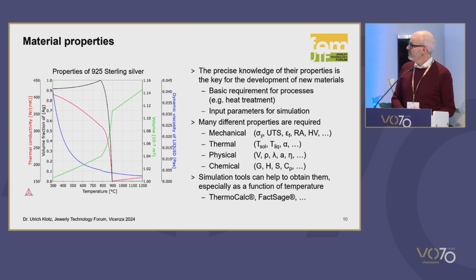And what parameters are around? We all know the mechanical parameters. They are quite easy to determine: tensile stress, elongation, hardness, reduction of area, and so on. Thermal properties we are also aware of: solidus, liquidus temperature, thermal expansion coefficient, and those properties are also not so complex to determine. But for the simulation tools, we need properties we are maybe not aware of, physical properties: the volume as a function of temperature in the solid and the liquid state, the density, the thermal conductivity, the thermal diffusivity, the viscosity, and also some chemical properties like Gibbs free energies, enthalpy, heat capacity. These properties are much more difficult to determine with standard laboratory techniques, but simulation techniques can help us to find them if we have good databases.